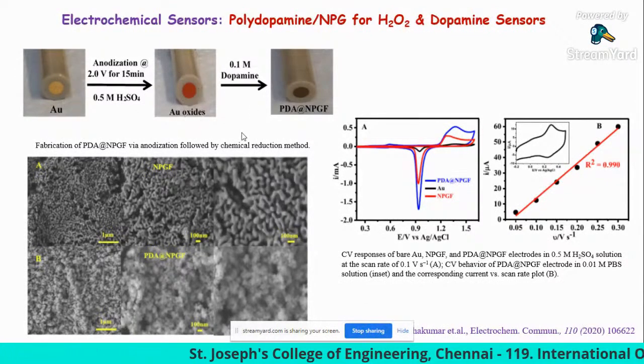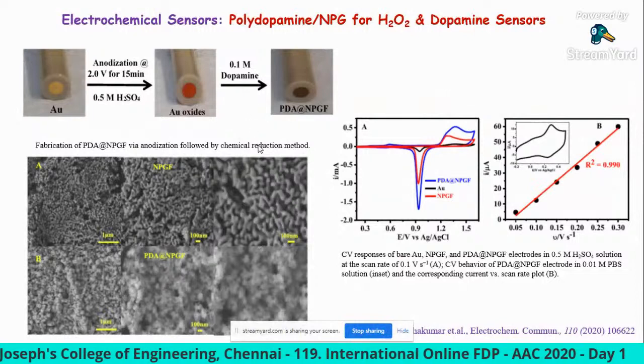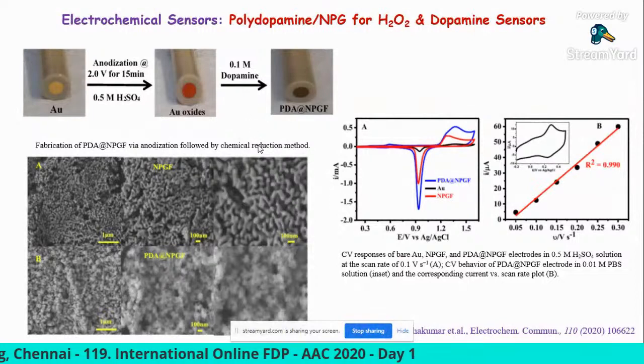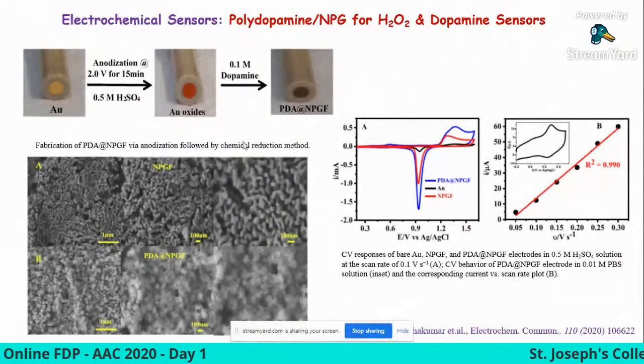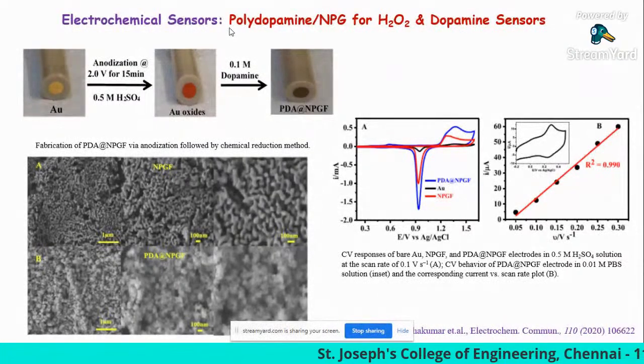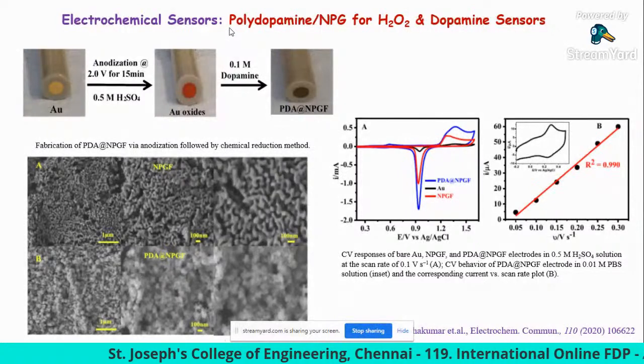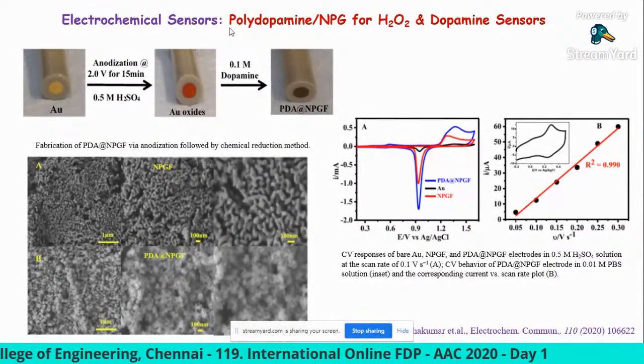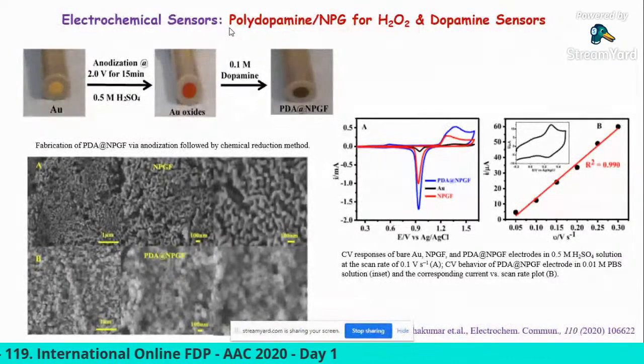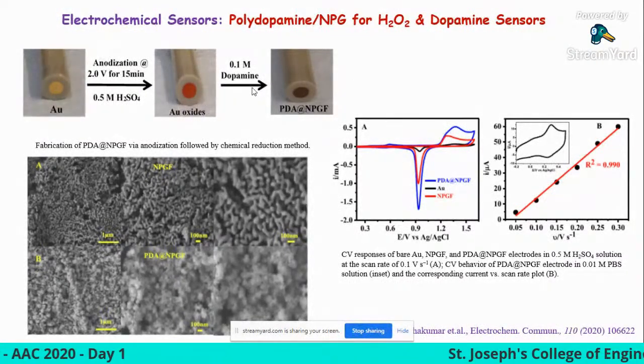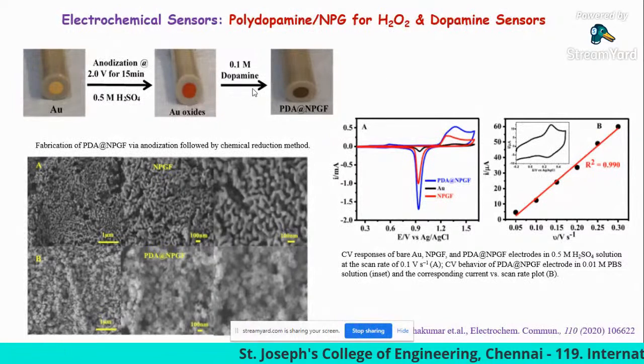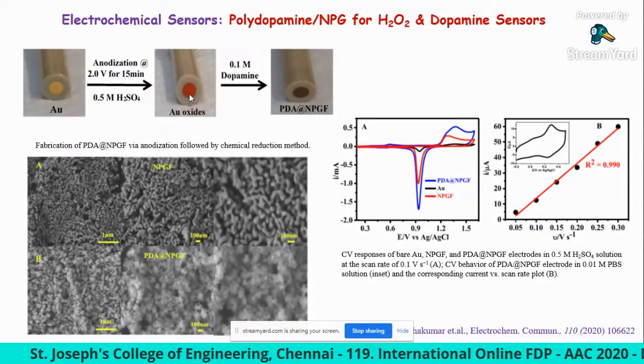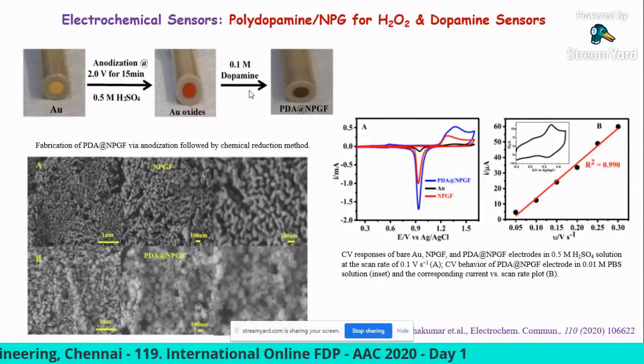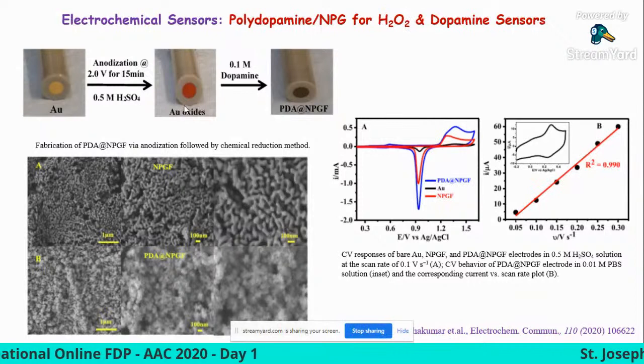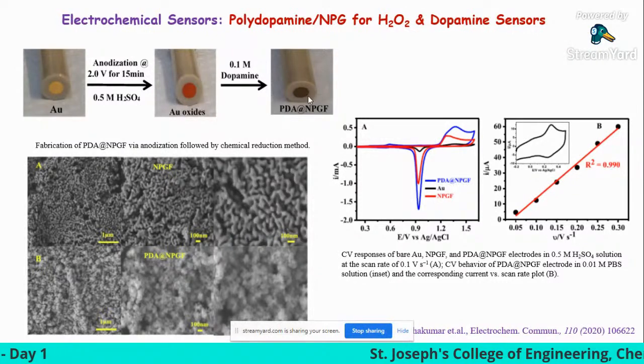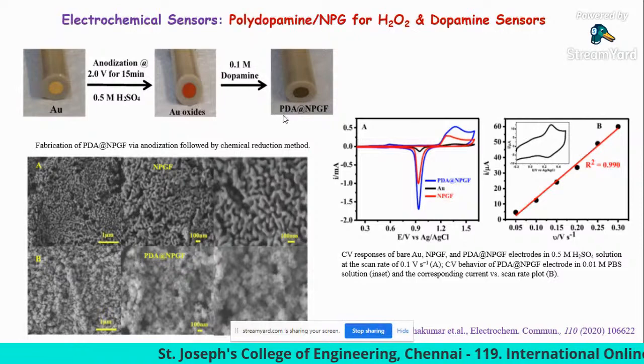After that, in electrochemistry, dopamine and ascorbic acid oxidize at the same potential. That is one of the big challenges, separating the oxidation of ascorbic acid and dopamine. Based on the literature, we thought, why don't we use dopamine instead of ascorbic acid? So one day we just tried this experiment, and we were very much surprised. When I immerse the Au oxide electrode in the dopamine solution, instantaneously the color of the electrode changes from orange to black, which indicates the formation of the nanoporous gold structure.